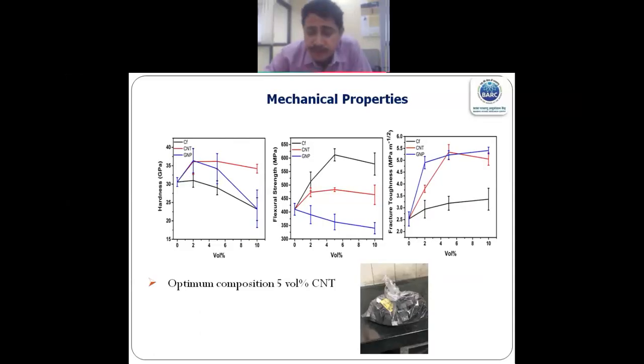But now I want to give you a comparison of these three materials, what we should use. Hardness, flexural strength and fracture toughness, all these three properties are very important for hard armor panel. If the fracture toughness is high, that means my energy is wasted by branching of cracks or bridging of cracks or crack deflection. So I can absorb more energy. So always we want a high toughness material, and hardness also high. If you see, the carbon nanotube with 5 volume percent gives you very good hardness, reasonably good flexural strength, and good toughness.